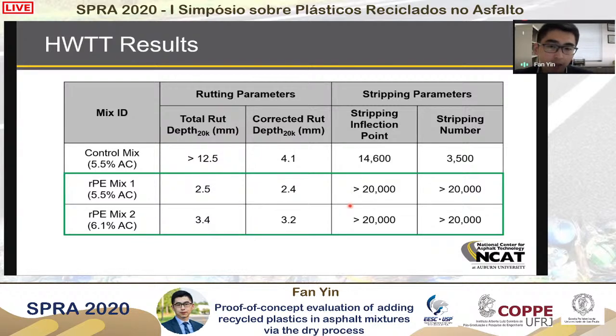Another thing we can get from the Hamburg analysis is the stripping, or the indication of moisture resistance. In this case, the control mix showed stripping in the Hamburg. Some fine aggregate got stripped out, separated from the binder due to adhesive failure, but we did not see that in the plastic modified mixes. So we're thinking that the plastic modified mix provides better resistance to moisture damage compared to the control mix, at least when we do the evaluation using Hamburg.